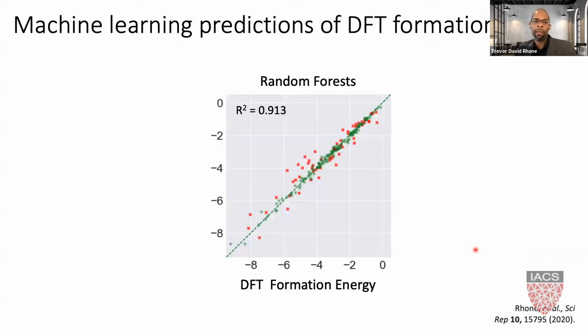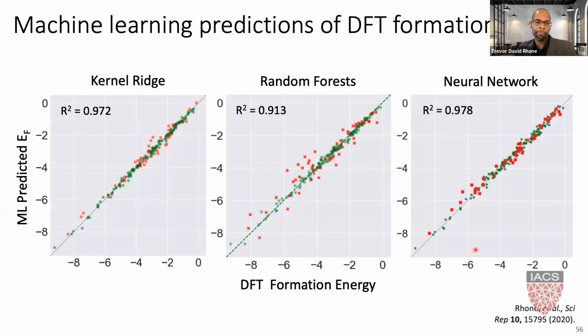So now we want to think about chemical stability via the formation energy. And not only do we want to be able to find new magnetic materials, we also want them again to be made in the lab and to be chemically stable. And so we went through and predicted the results for the chemical formation energy for the random forest model, and also models including the kernel ridge regression model and neural networks. It turns out neural networks surprisingly has the best prediction accuracy.